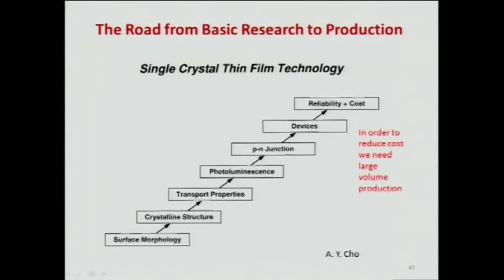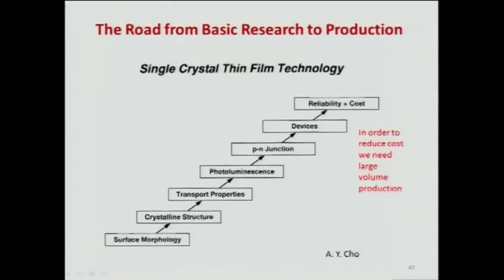I would like to say how I finally tried to reach my dream of developing MBE for production. As we know, in the crystal growth area, anybody can start growing a crystal and look at the surface morphologies, and then you can publish a paper. Therefore, this is the first step. We can look at the surface morphology, do some measurements, and then publish. The next thing is harder: to look at the transport properties. And if you have traps in there, the mobility is not high. So you have to make the layer a little better to have high mobility materials.